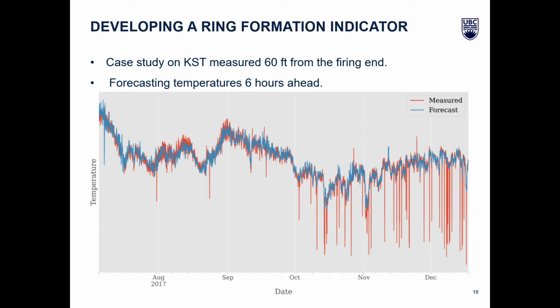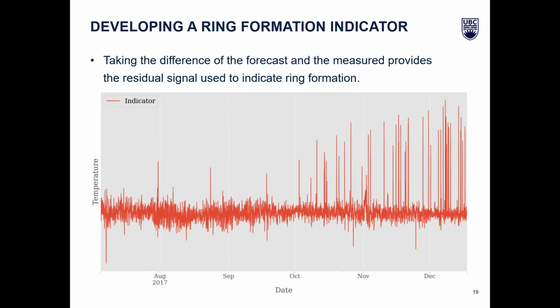The time series model operates with a moving window such that it produces a forecast with a 6-hour moving horizon. This slide shows the residual generation that was discussed before. The signal presented here is created by simply taking the difference between the forecasts and the measured shell temperatures. Note that the big upward spikes shown in this signal correspond directly to the uncharacteristic downward spikes that were observed in the shell temperature measurements.